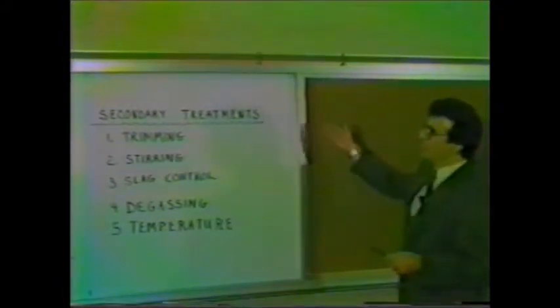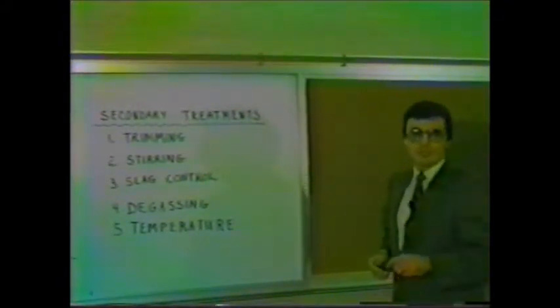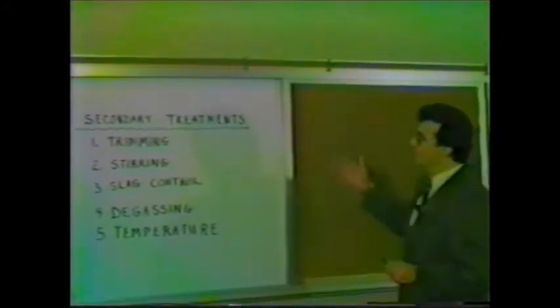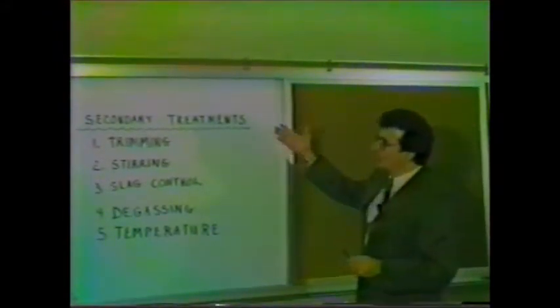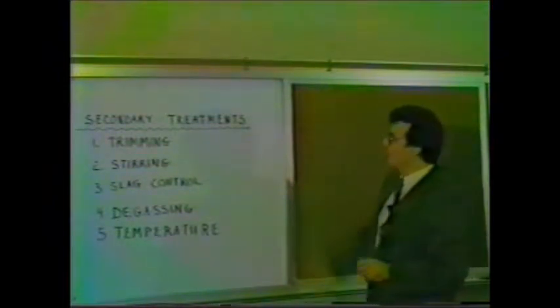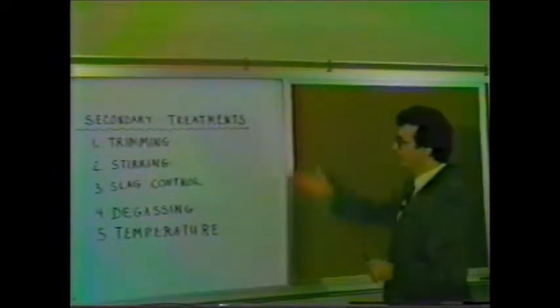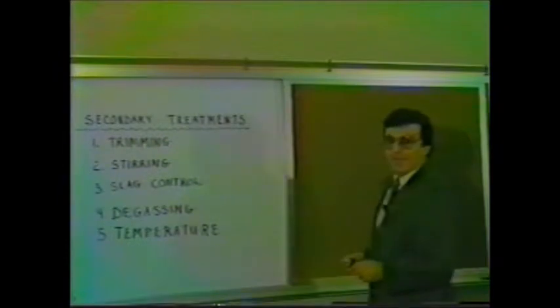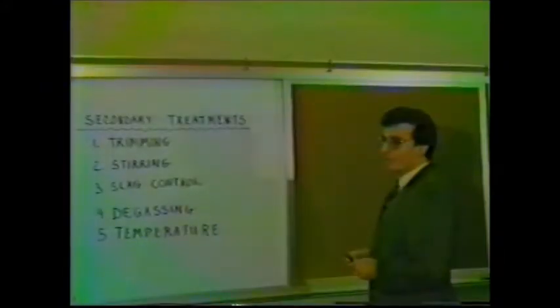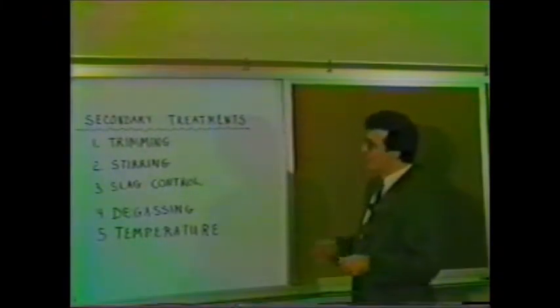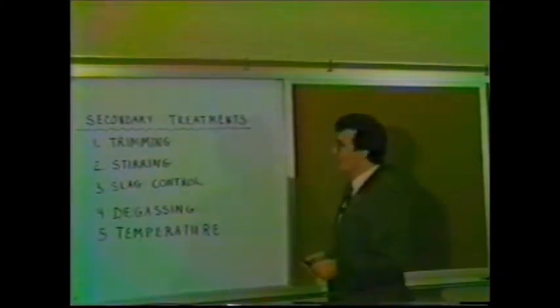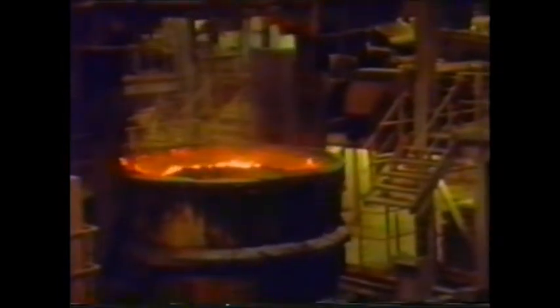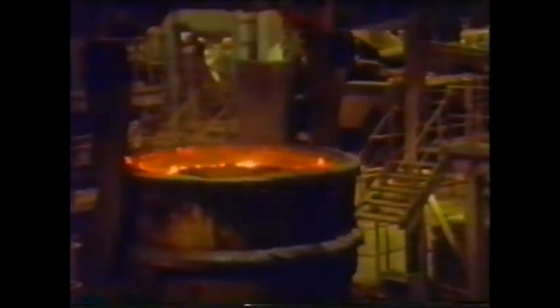Now, these are treatments while the steel is still liquid, just after the steel has been made and is still in the ladle. These are not mandatory, but optional treatments that can be done to the steel, and they are listed as follows. You can trim the chemistry of the steel, and bring it into the ordered range by adding little additions of certain elements. You can also use either induction stirring or electromagnetic stirring, and the purpose of this is to distribute the bath composition more evenly within the ladle.